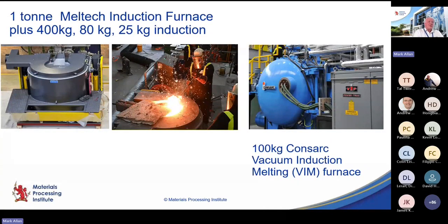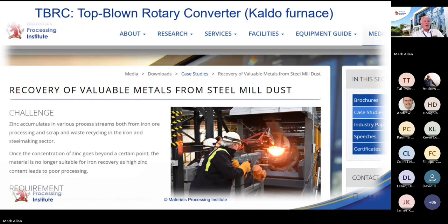Of course, not every melt is done at that scale, and we have other melting facilities, including induction melting, where at laboratory scale, the smallest thing we could melt is about the size of a baked bean, ranging up at the upper end to 1 ton induction melting open to atmosphere, or we also have a 100 kilogram vacuum induction melting facility, which tends to get used for some of the ultra high purity grade development work for customers such as the nuclear sector. And it's not only steel that we melt.